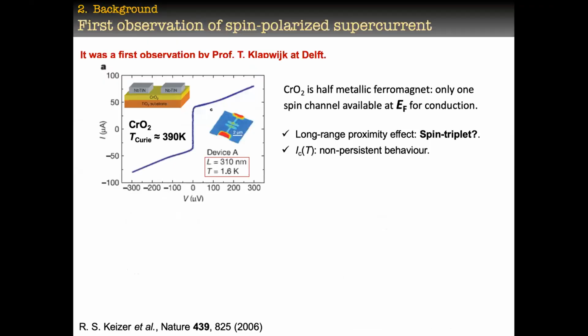But in 2006, from Delft University, the group of Professor Klapwijk actually did the first experiment using chromium dioxide. Chromium dioxide is a very interesting material because it is fully spin polarized, meaning that in this material only one spin channel is available for conduction. So what does it mean? It means that Cooper pairs with a spin up and spin down can never penetrate this material, only spin up, because there is only one spin channel, okay?